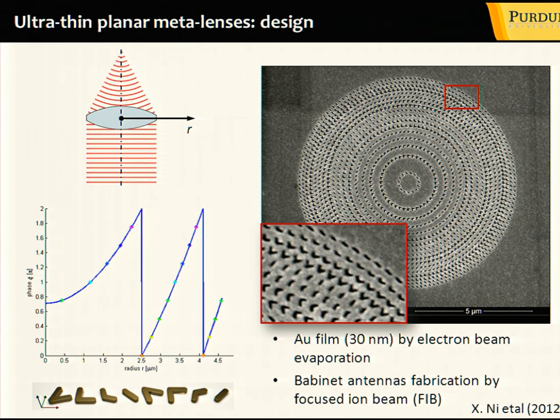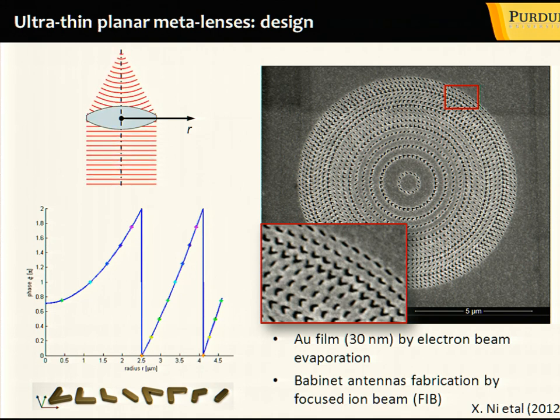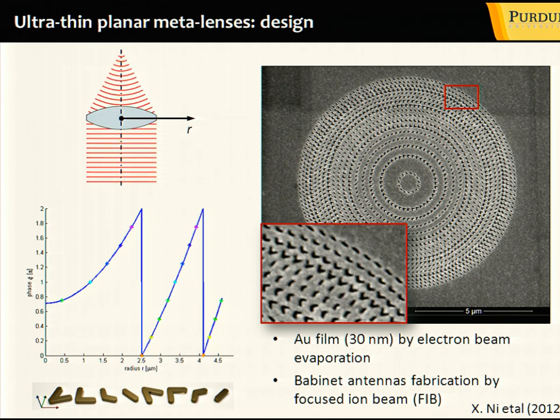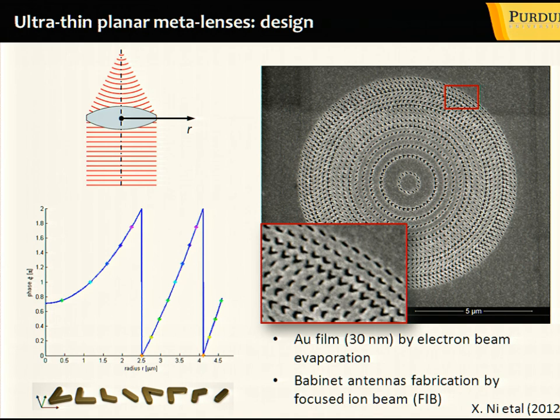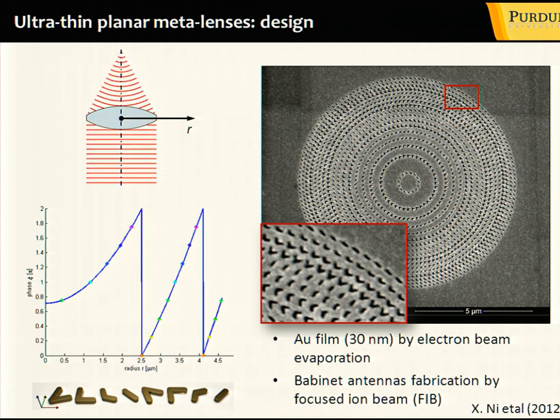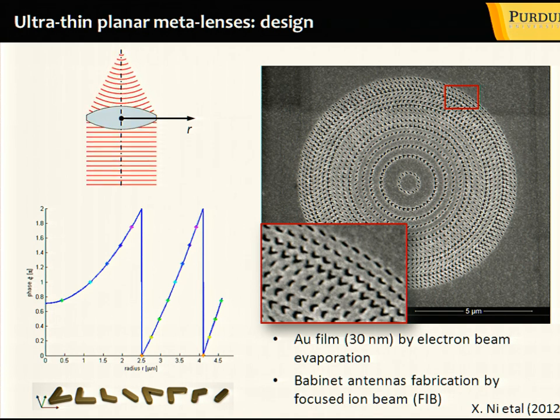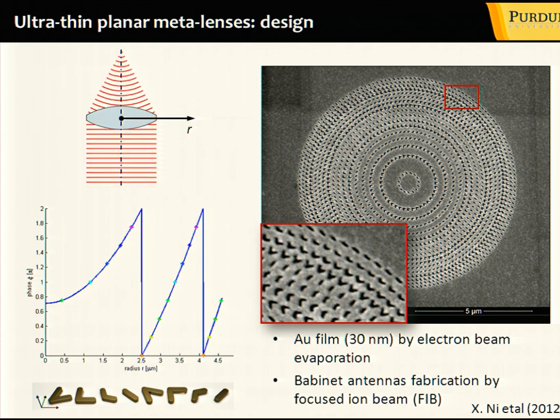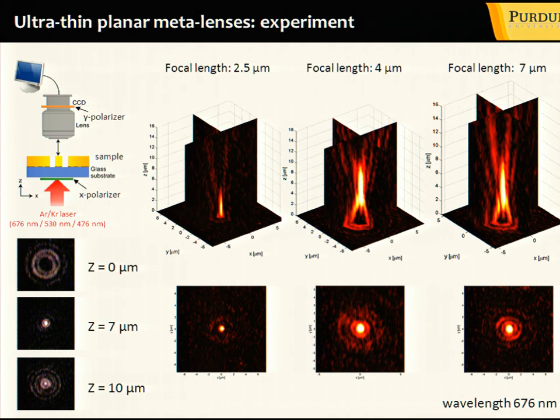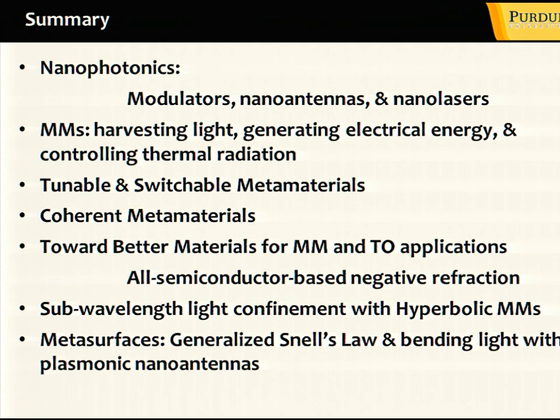Well, you could also make a metalens. This is a recent experiment done by Xingjie Ni in my group. So he used these V antennas to make this metalens. You could see that you introduce a very strong gradient of phase, shown here as a function of radius. You change it by 2 pi, and you could make it so that constructive interference occurs at any point beyond the lens. So here you could see, for example, that this lens has extremely strong focusing ability. It focuses light, depending on what kind of metalens you use, 2.5 or 4 micron behind the lens and to a spot which is comparable in size to the wavelength. This is just one example, but there are plenty of other very interesting applications related to metasurfaces.